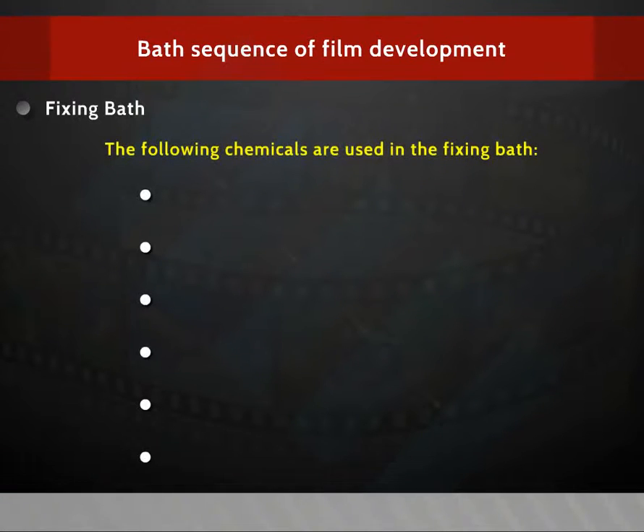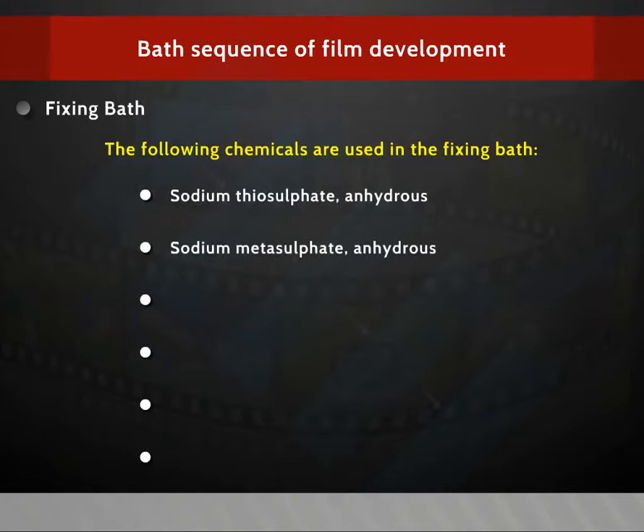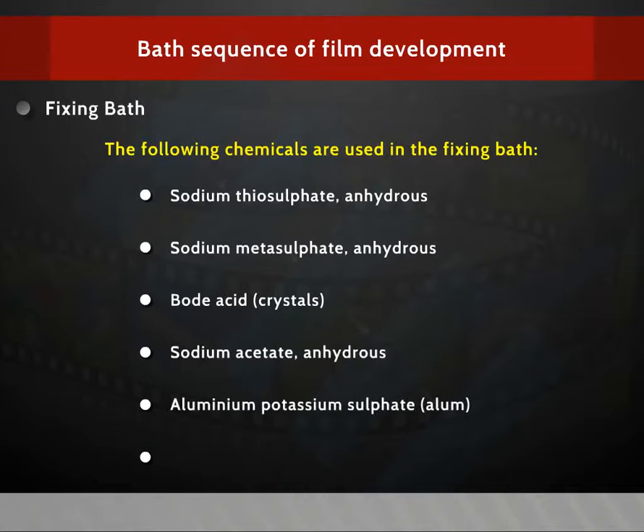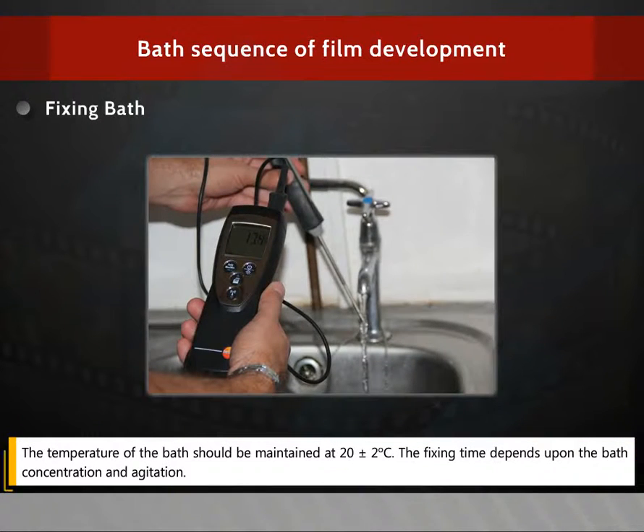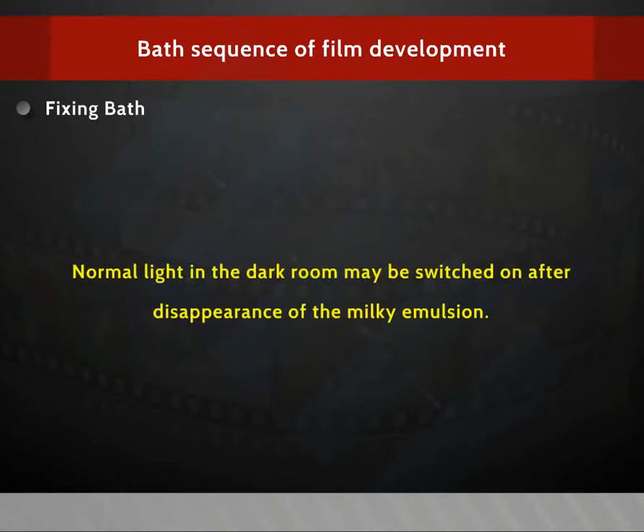The following chemicals are used in the fixing bath: sodium thiosulfate anhydrous, sodium metasulfate anhydrous, boric acid, that is crystals, sodium acetate anhydrous, aluminum potassium sulfate, that is alum, and distilled water. The temperature of the bath should be maintained at 20 plus or minus 2 degrees Celsius. The fixing time depends upon the bath concentration and agitation. Normal light in the dark room may be switched on after disappearance of the milky emulsion.